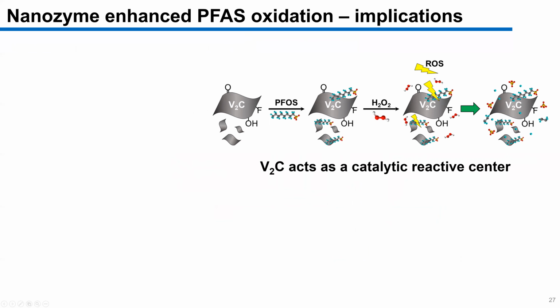Okay, so the formation of the solvated electrons, we think, is what initiates the PFAS degradation, because we know, again, from literature that without solvated electrons, you're not going to get that level of PFAS degradation that we observe in our study. So what we think is happening is that the vanadium carbide nanosheets are serving as a catalytic reactive center for PFAS degradation. So first, we suspect that PFAS adsorbs to the vanadium carbide nanosheets, and that again is